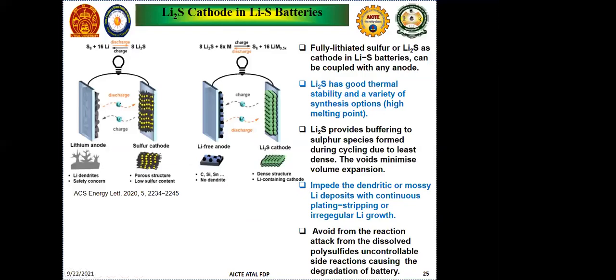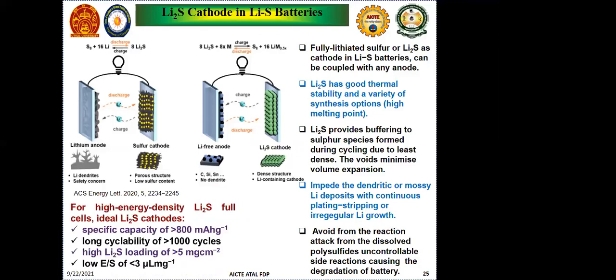Please proceed. Even when we use the lithium sulfur based cathode, as I said, there is a problem in stability of the sulfur, and the sulfur content is reduced when there is a huge amount of polysulfide formation. So we can think of Li2S cathode materials, because no doubt it gives a high specific capacity and long cycle, because this Li2S cathode will be a dense structure, and it will contain a sufficient amount of lithium and sulfur. And the major factor is that we have to adjust the lithium and sulfur balance in this lithium sulfur system.